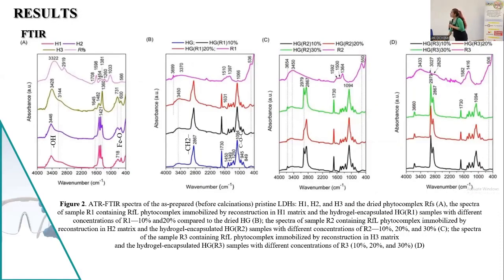So as results, the FTIR results show that in the LDH spectra, we can find the characteristic peaks of the stretching vibration of OH and iron-oxygen bonds. Also, we can find some different bands depending on the type of the LDH, which is due to the absence of calcium from the brucite-type layer, and also to the bidentate configuration of the carbonate anions. Also, we can observe in the spectrum of the phytoextract the characteristic stretching vibration of the OH and the aromatic CH groups.